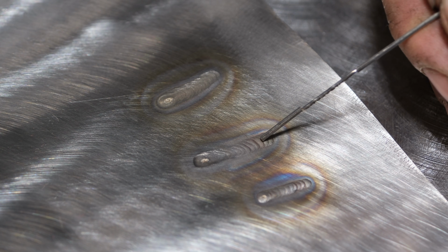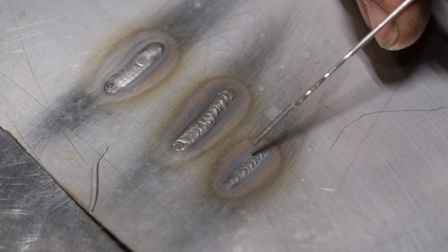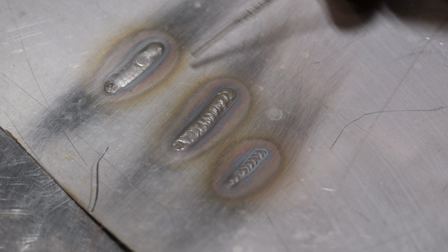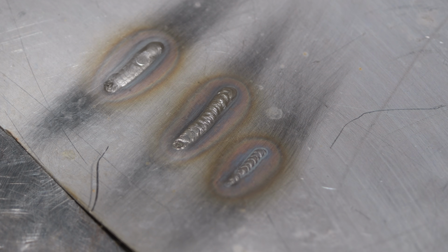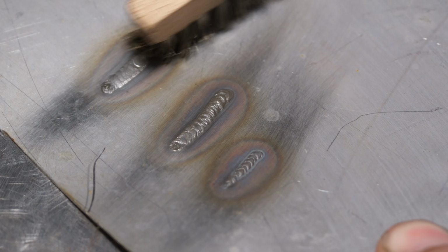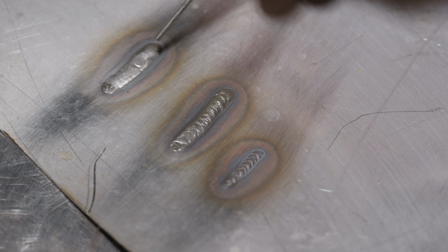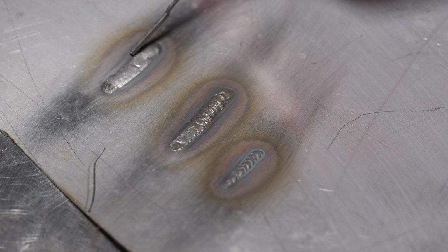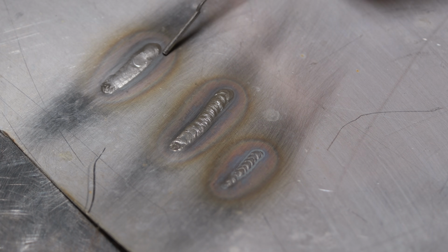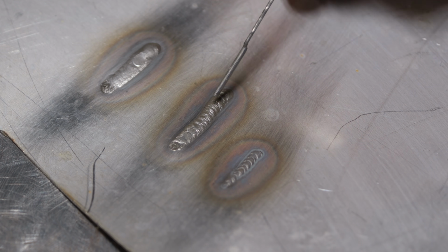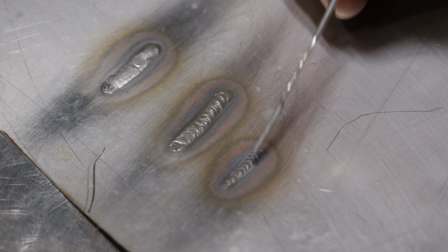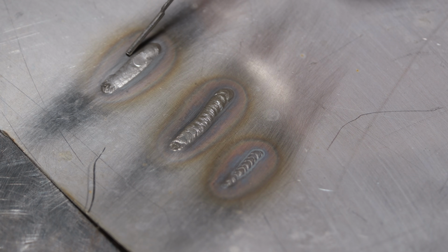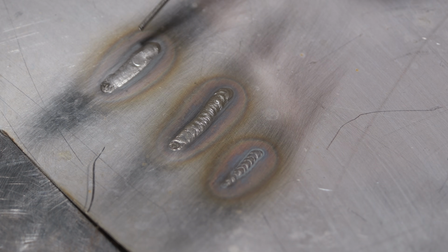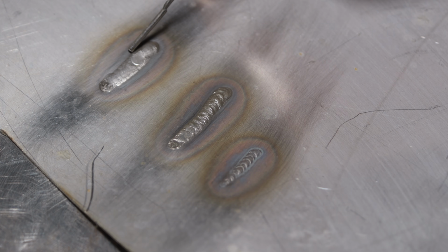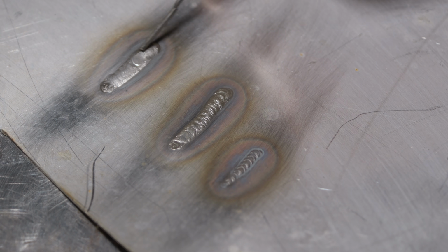Now let's take a look at the back side at what we have. So here on the back side, I took the liberty of brushing these welds a little bit, and you can see what we have here. Basically, all the oxidization colors are gone. However, there's this gray area that you can see around the weld, here and here, even internally on the bead there. All of that is oxidization of the stainless that will rust. This is why with stainless steel, to get an absolute clean backside of a weld, you must purge it with argon so that it cannot react with oxygen in the air and have this happen.